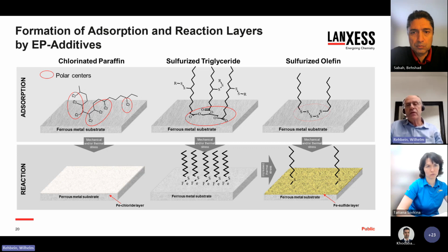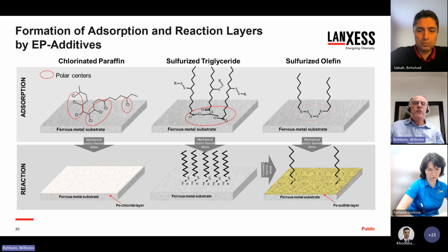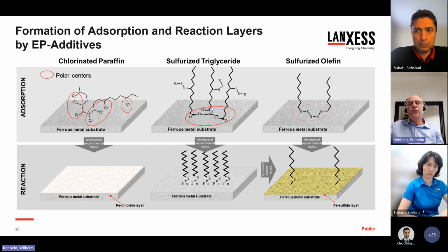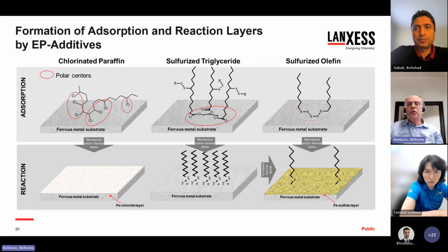So according to the common theory, in a first step, they physically adsorb on metal surfaces with their polar centers. And by this, they are already forming a kind of friction reducing layer. And with increased mechanical stress, that is usually followed by thermal stress, they chemically react with the metal surfaces, forming protective layers that are less shear stable than the metal structure itself. And by this, they prevent the metal surfaces from galling or cold welding.